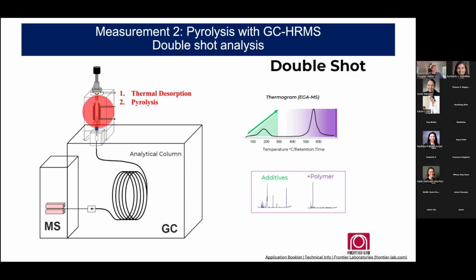So I'll move quickly through the rest of this since we only have a few more minutes. But one of the ways we avoid this, and also to embrace the complexity of what we're measuring, is we integrate two separate measures using the pyrolysis system on our instruments. This approach is called a double shot analysis because when we're characterizing our samples, we first heat them to about 300 degrees. And this will cause many of the additives or other environmental chemicals to be released from the plastic particles that are in the sample.